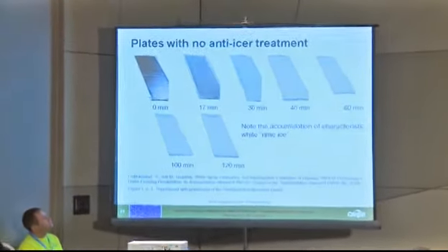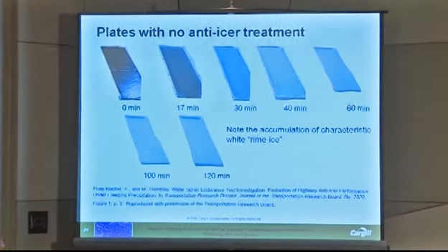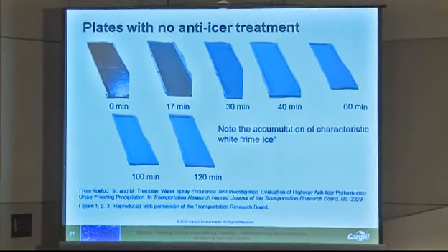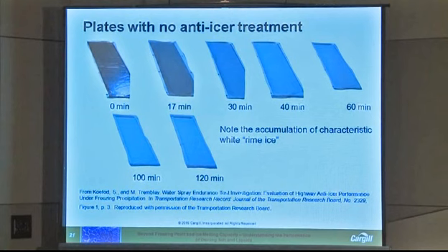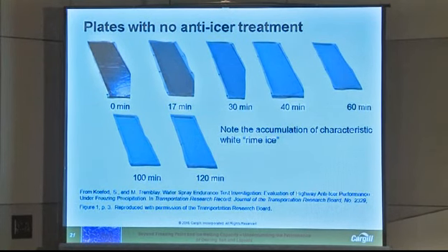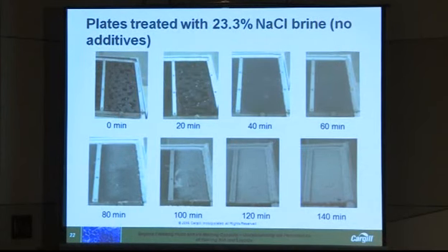If there is no de-icer on the surface, what we see is there is an immediate and rapid accumulation of this very characteristic white snow-like rime ice. Now compare that to what we see if there is a de-icing fluid on the plate. In this case, we're looking at a plate that's been treated with plain salt brine. Now after 20 minutes of freezing precipitation, note that there's no white rime ice present. Of course, that's just what we would expect. Because the de-icer is there, it's melting the precipitation.